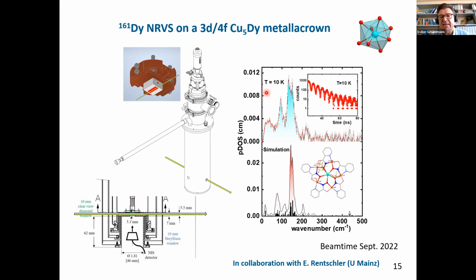Here's an example. That's a measurement done in September on another type of SMM, a dysprosium-containing metallacrown. The structure is here with some coppers outside here. And the DFT simulation, which was done afterwards, fits very well to the spectrum here. And the advantage of this is we can do top loading. So in that system, you can also load very oxygen sensitive samples. And the dysprosium CP systems, which have records now, are, as far as I know, quite oxygen sensitive.